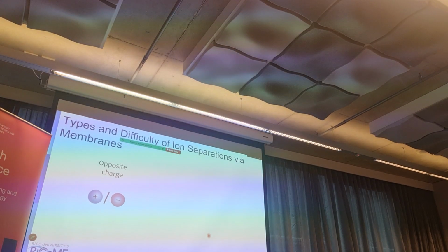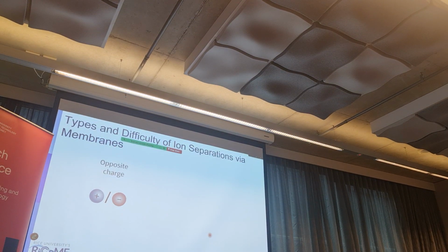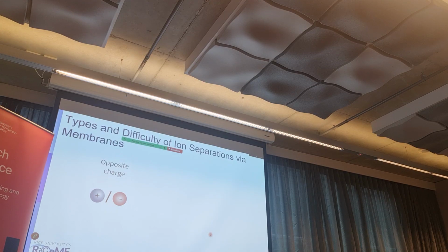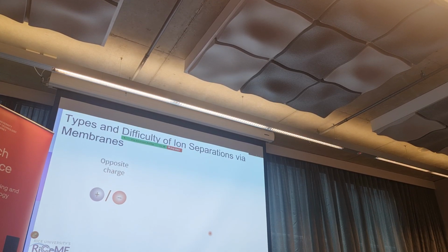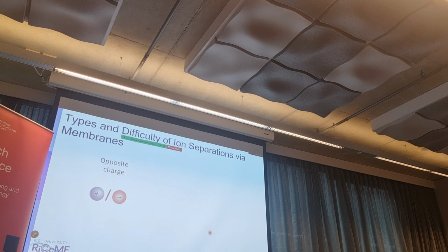We can just use ion exchange membranes in electrodialysis, and then the cations will go to the cation exchange membrane, anion to anion exchange membrane, and we can get very high selectivity. So this is not an issue there.